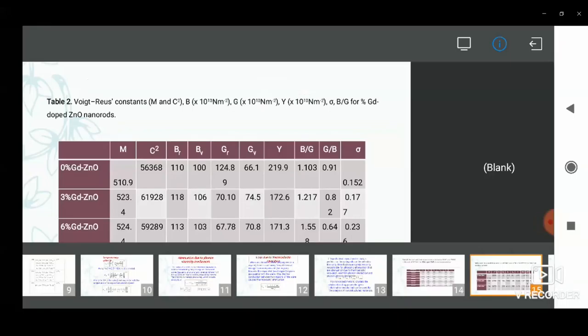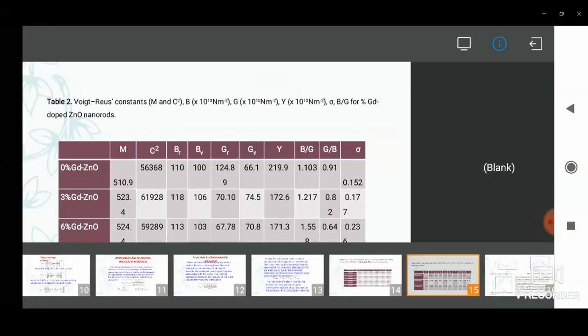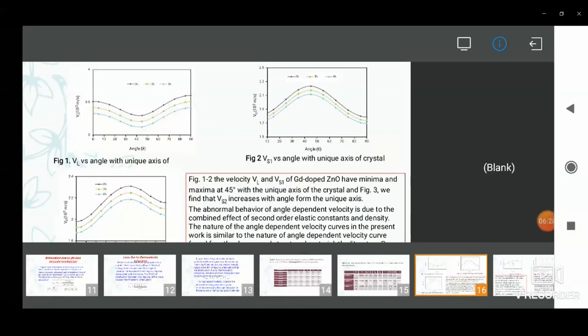This is 0% Gd-doped zinc oxide, 3% Gd-doped zinc oxide, and 6% Gd-doped zinc oxide. Figure 1 shows the velocities VL and VS of the Gd-doped zinc oxide having minima and maxima at 45 degrees with the unique axis of the crystal. In Figure 3, we find the VS2 increases with angle from the unique axis. The abnormal behavior of the angle dependent velocity is due to the combined effect of the second order elastic constants and density.